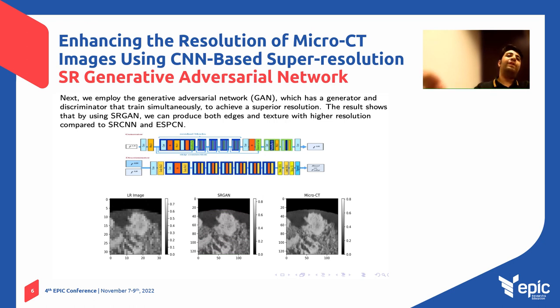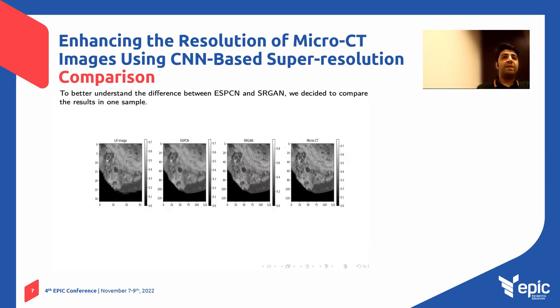You can see the super resolution image generated from the low resolution input is very close to the real image. In the comparison between ESPCN and SRGAN, SRGAN has much better accuracy in generating micro-CT images with more elaborated structure, while ESPCN has the advantage of taking much less training time due to its shallow architecture and still does a great job capturing the details of the high resolution image.